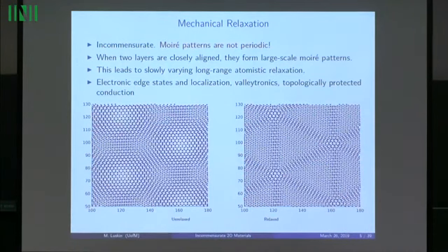Okay, so now I'm going to develop a model for the relaxation. The model is simply going to use linear elasticity for the intralayer interactions. So each layer itself, I'm going to have a very simple linear elastic model. You can have more sophisticated things, but it's going to be very simple. But the interlayer interaction, that's where this disregistry comes in. So that means the layers are going to want to shift to try to find that low energy state.